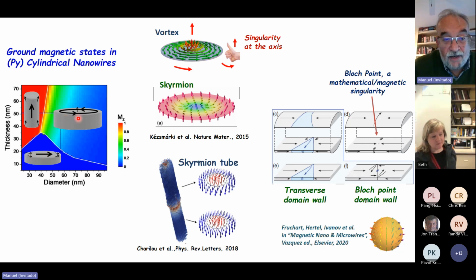The vortex is characterized by this azimuthal magnetization, but at the very axis it has to be axial. Depending on the geometry, the aspect ratio, length to diameter, we can have different ground magnetic states. And also in the nanowires, here is repeated the figure of the vortex. We have a magnetic singularity in the axis because of the exchange energy restrictions.